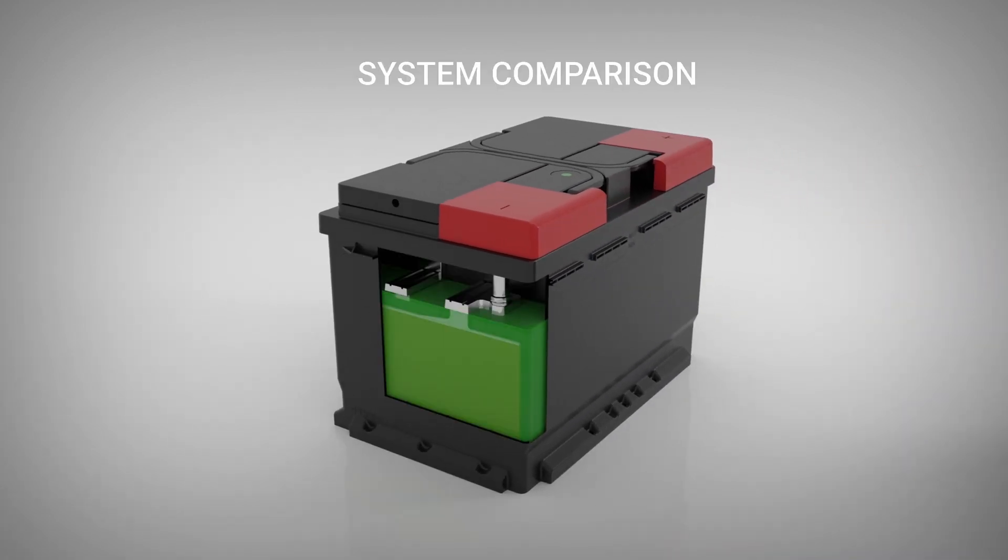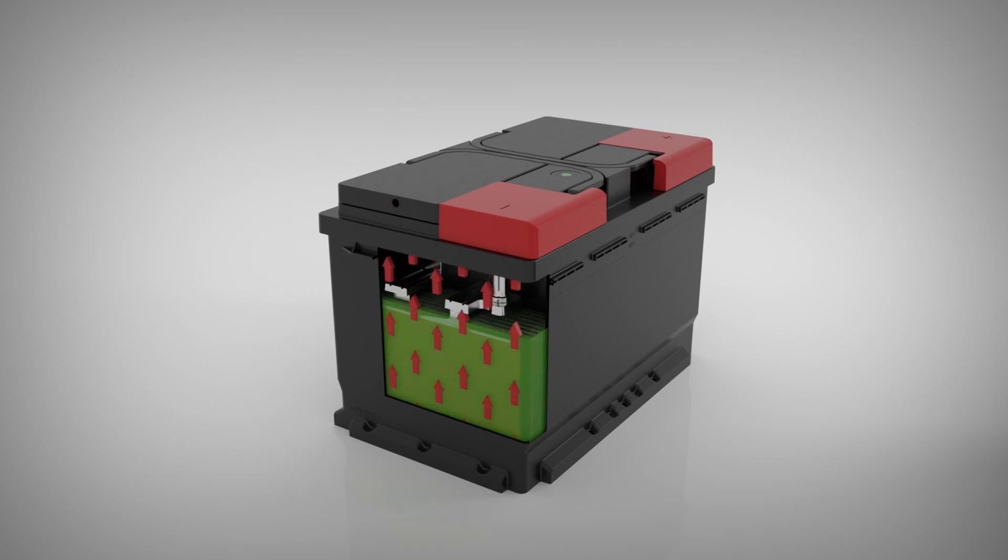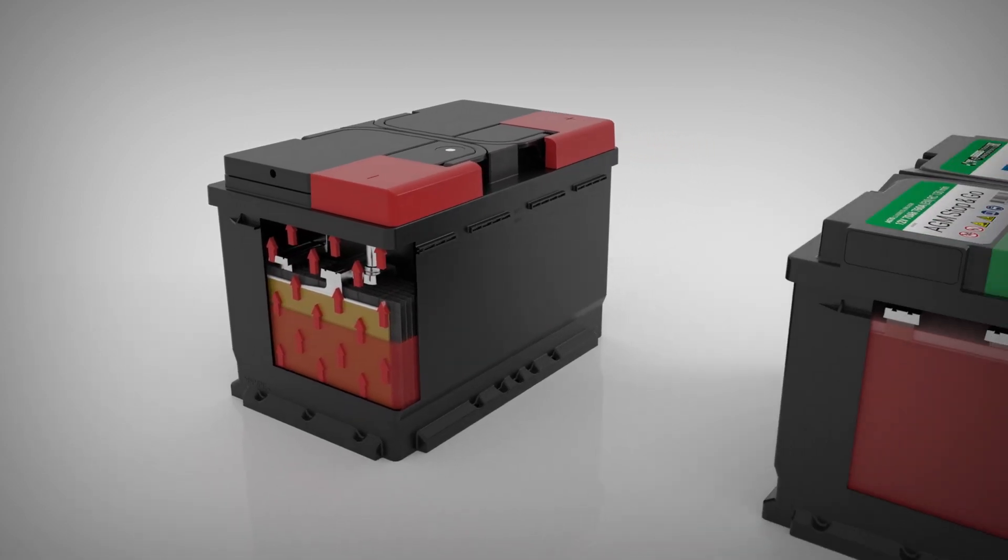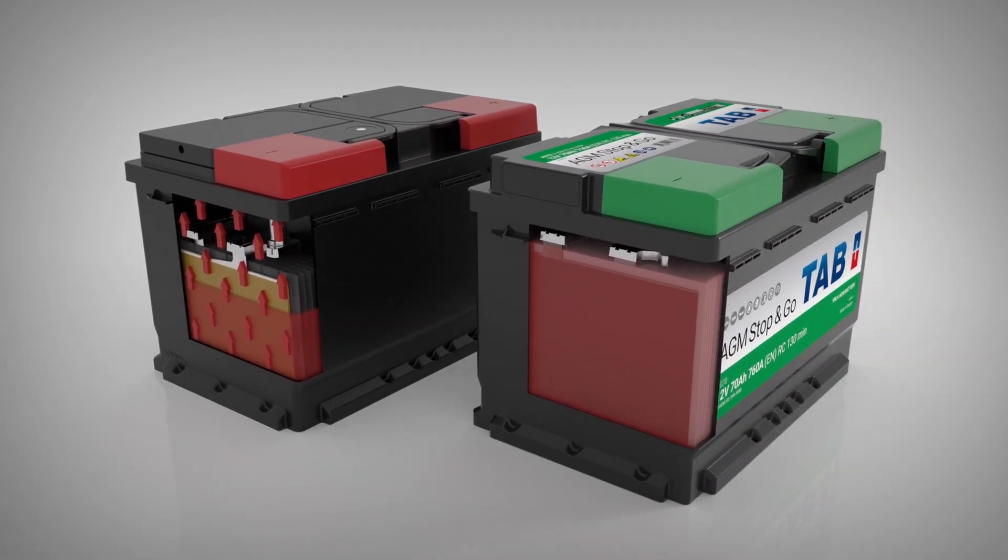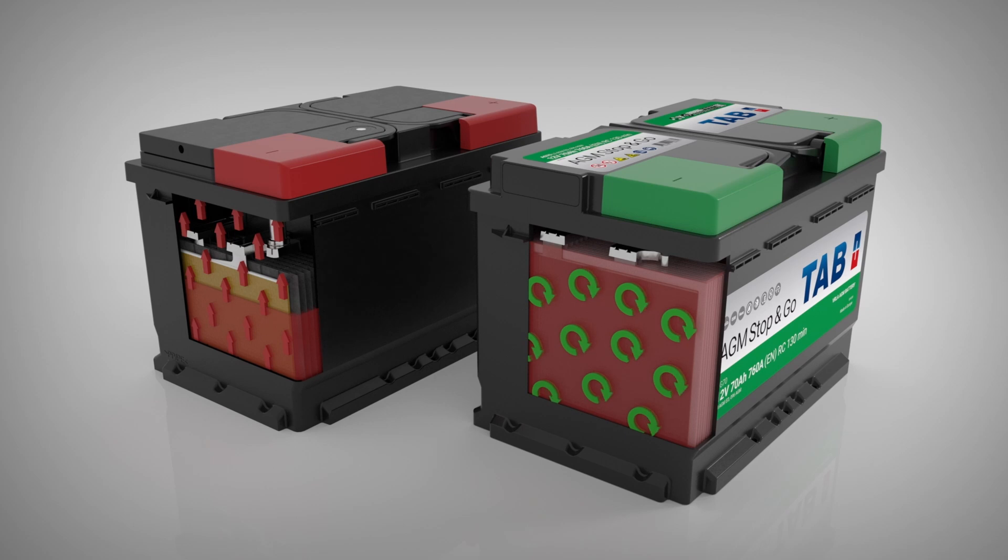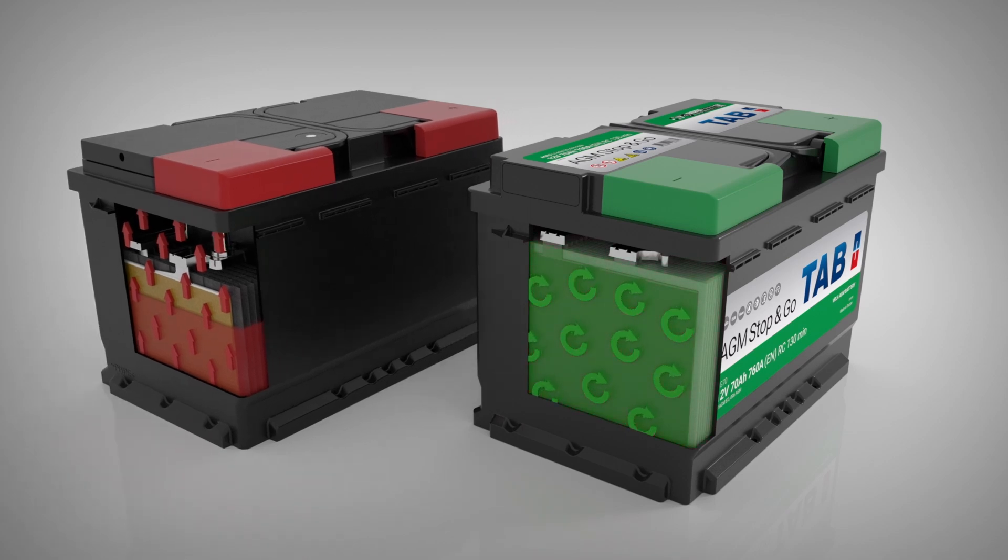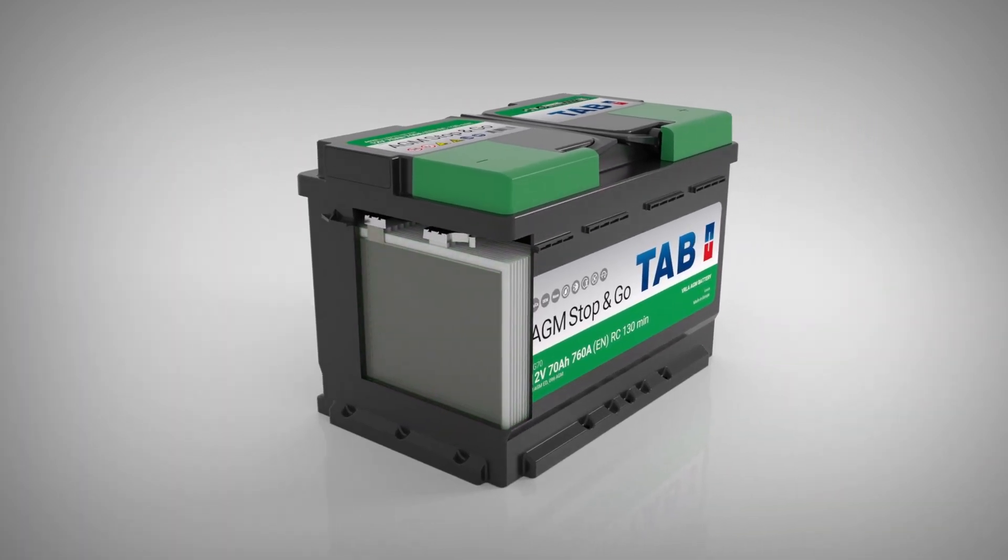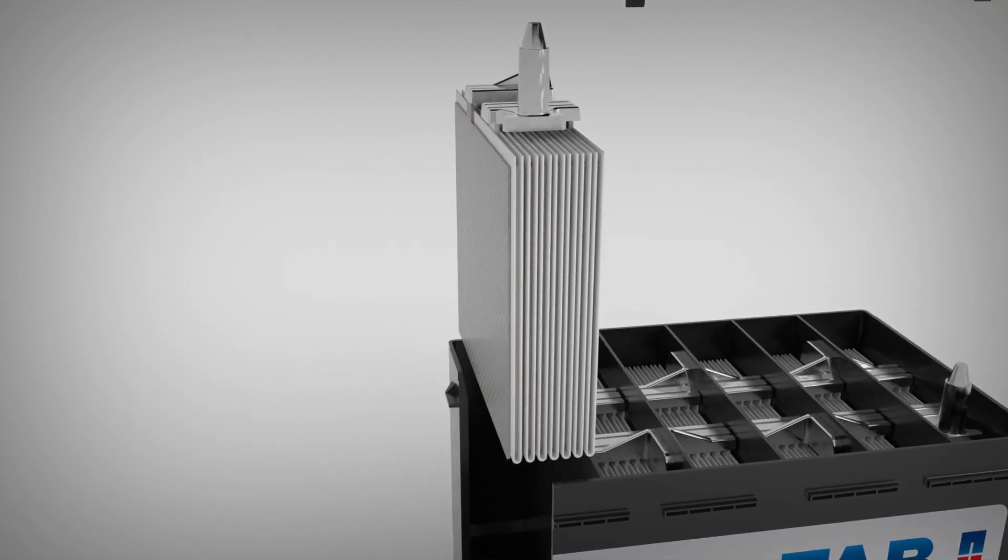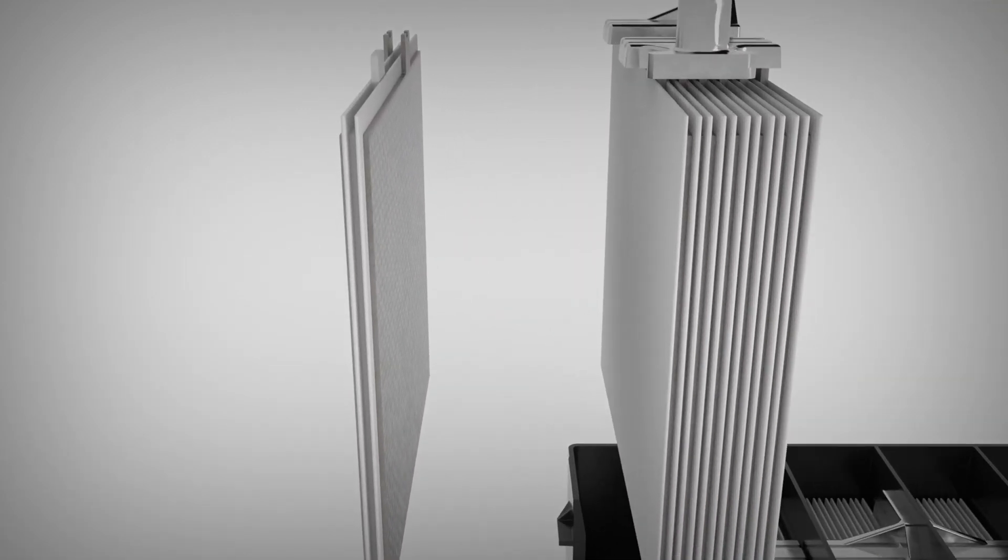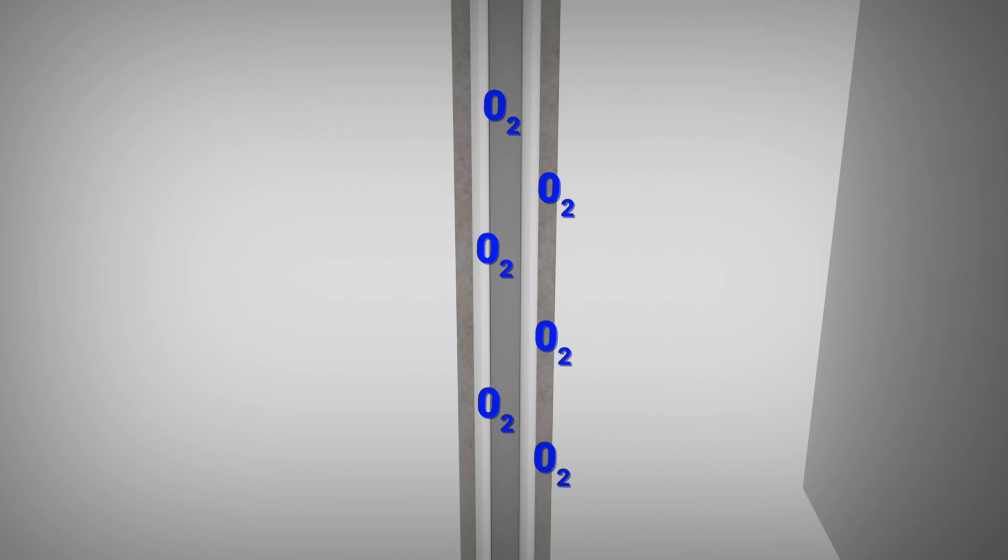In a flooded battery, the gases are vented above the cell and out of the battery. The dissipated gases represent a loss of water from the electrolyte. An AGM battery has an internal oxygen recombination cycle where the evolved oxygen is transferred through a gas space to the negative plate where it is returned to water. The essential function of the TAB AGM battery relies on the transportation of oxygen from the positive plate through the separator to the negative plate during charging.